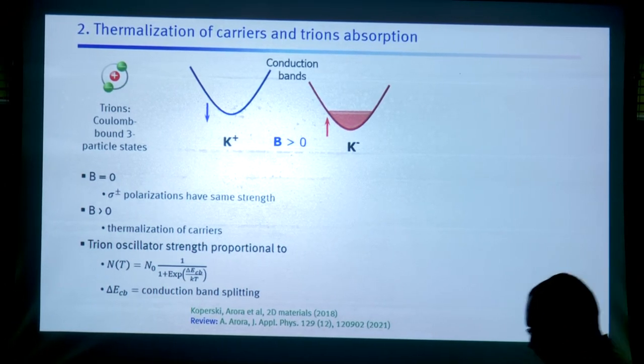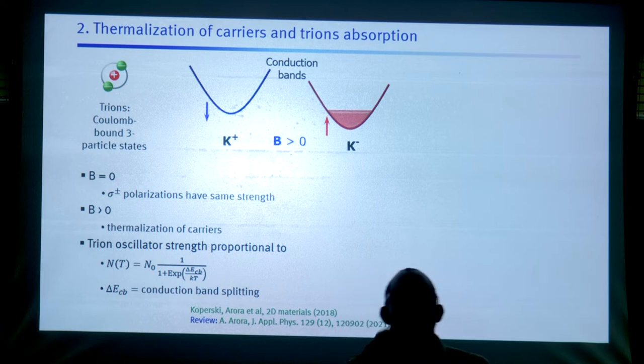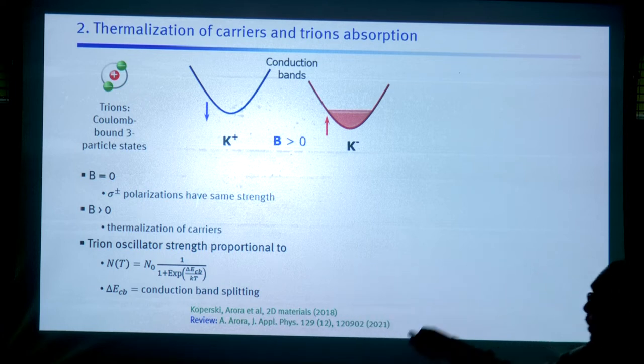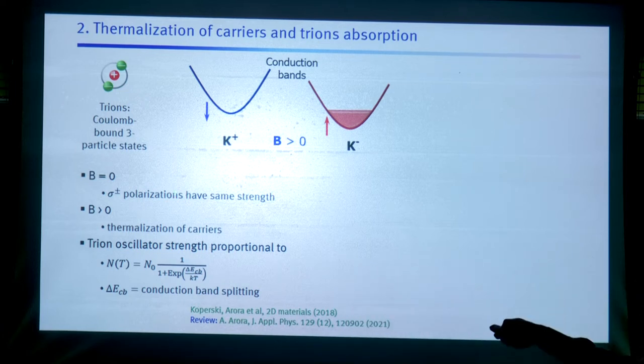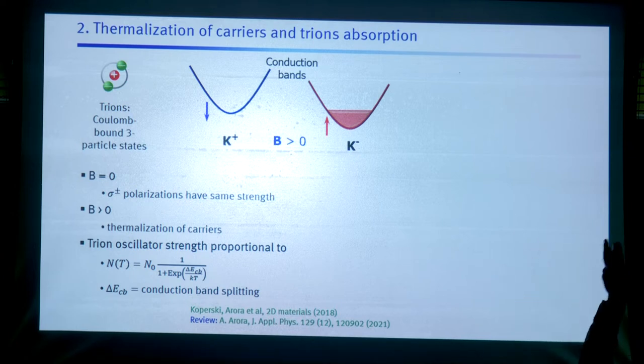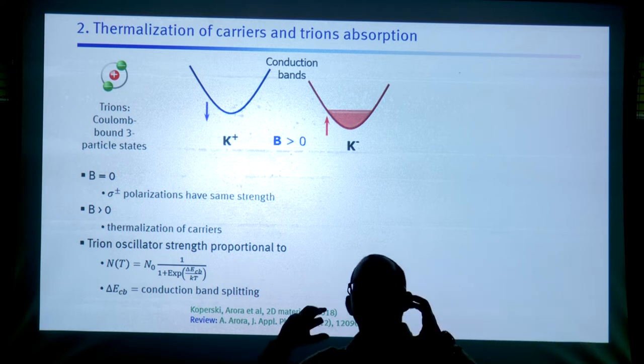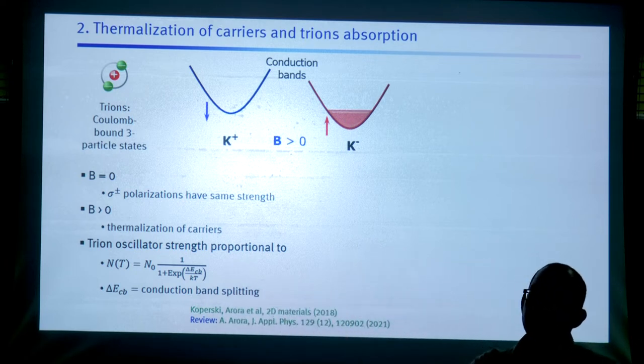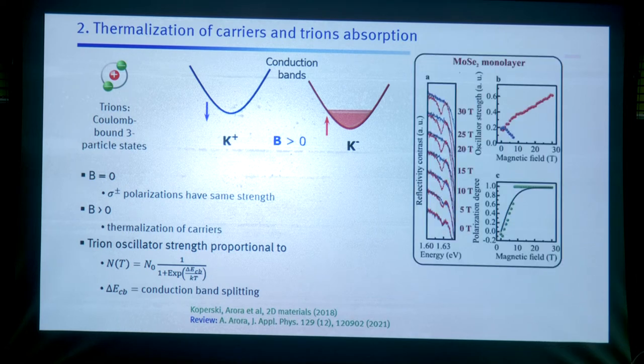Secondly, since we are creating these trions, they have an optical signature, so they show up in the reflectance spectra. The trions in this valley should vanish, and in this valley they should gain a lot of strength, because now they have extra charges only in this valley. So one of the circular polarizations should be very bright, and the other circular polarization should just go away. This is exactly what we saw.